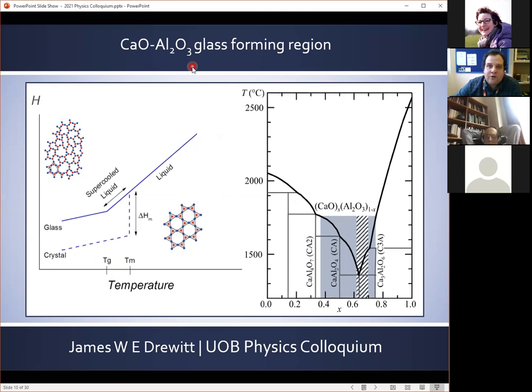We consider liquid alumina, Al2O3, shown here on the left of this phase diagram. It doesn't on its own form a glass. It just has the wrong stoichiometry. It's unable to form a glass material. However, we can add other cations, other oxides, to alumina to form glass, and so in the calcium aluminate system, this hatched region around the eutectic represents a traditional glass forming region.